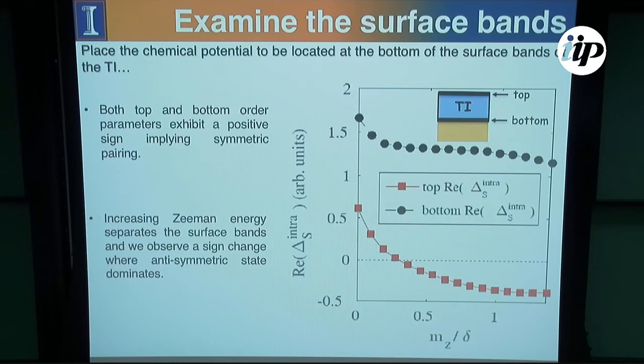So we have the top and bottom surfaces. What I wanted to do here was see, using the simple analytic model, and sure enough, this is looking just at the S-wave component. As we increase the Zeeman energy, you get this pairing in between these two. This is top and bottom, and we can see that the S-wave order parameter for the top surface changes. This is because as we transition through this Zeeman term, we go from a symmetric combination to an antisymmetric combination.